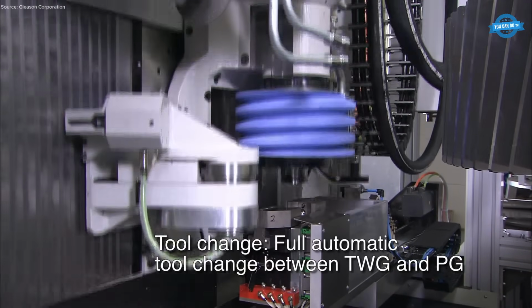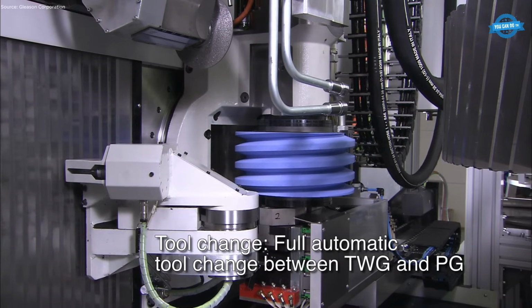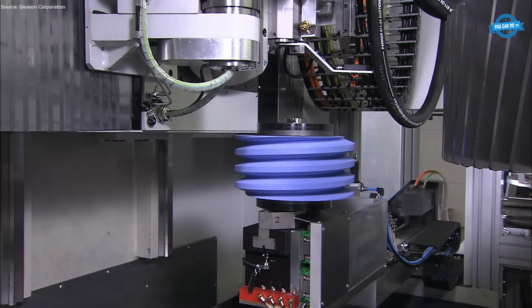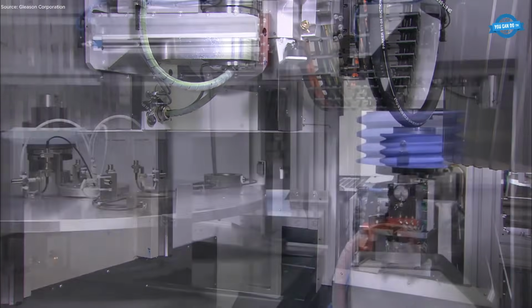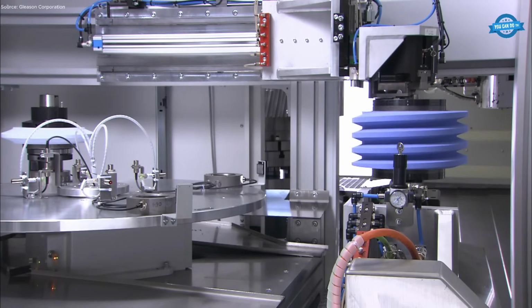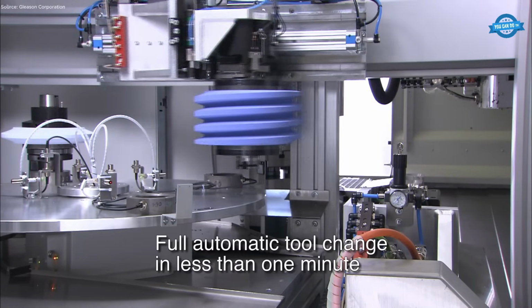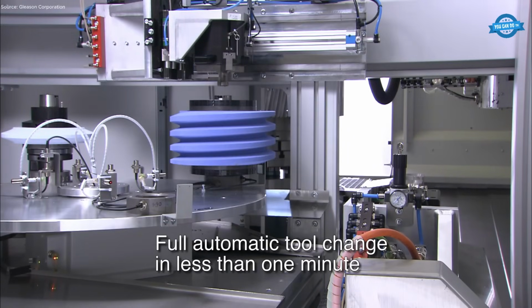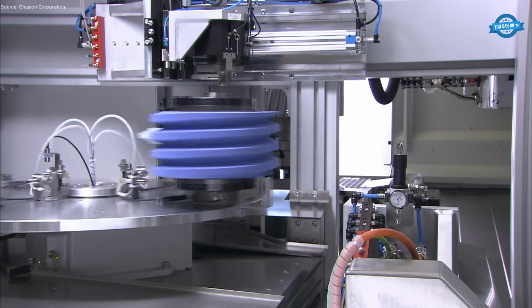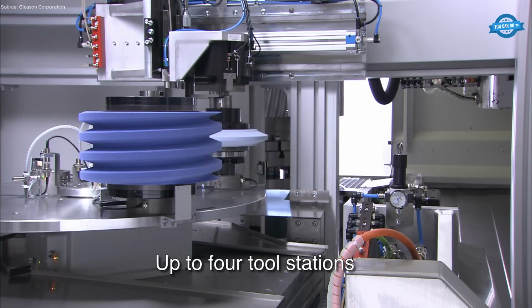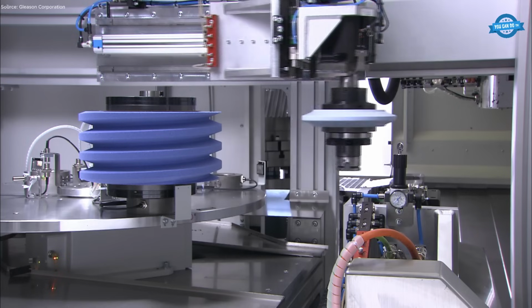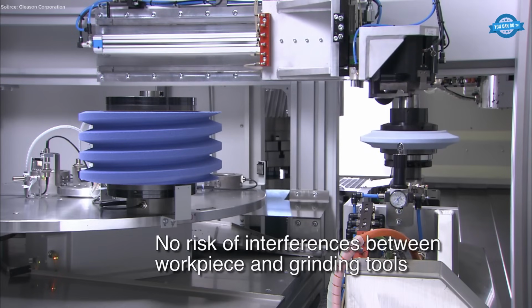In the roughing stage, a coarse grit threaded wheel is used for maximum material removal rates. For example, with module 14, 84 teeth, face width 255 mm, helix angle 11 degrees, the Titan Power Grind achieves up to 36% faster cycle times compared to conventional profile grinding without compromising accuracy.